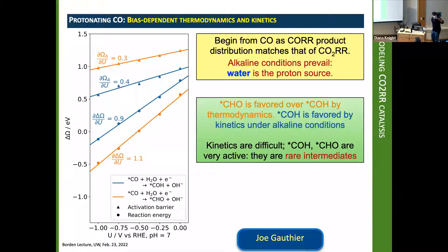On the other hand, the kinetics are still quite difficult. And the more favorable intermediate, star CHO, has the less favorable kinetics. And in fact, a barrier of 1 volt means very difficult kinetics. Furthermore, the barrier significantly lower to the star COH means that one should form that preferentially. The difficult kinetics and the fact that the subsequent steps are a cascade downhill in free energy means these species will be rare.